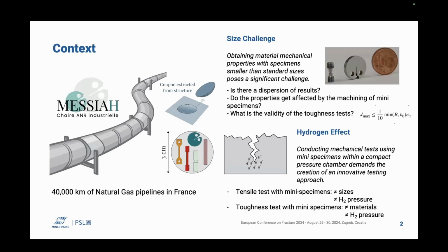We could also have dispersion of the results because they are very small and could be taken from separate parts of the material. And also there is the validity of the toughness test, because we know that the validity of toughness tests is also related to the thickness of the specimen. And as if that was not enough, we also have the hydrogen, because we intend to do this test with gaseous hydrogen. So we have developed an innovative test setup to perform tests of mini specimens in gaseous hydrogen. Today I will present some results of tensile tests with mini specimens, different sizes of specimens, and different hydrogen pressures, and also toughness tests with mini specimens with different steel pipeline materials and different hydrogen pressures.